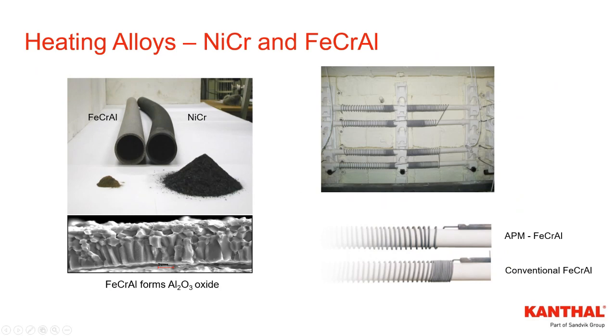And also there are details on differences between the creep strength of the materials. So depending on the alloy that's used, you might get bunching of a coiled heating element. This bunching could result in overheating and shorter life. This is just to show the differences between different grades of iron chrome aluminum. You might get less bunching or more bunching depending on what grade of alloy you're selecting.